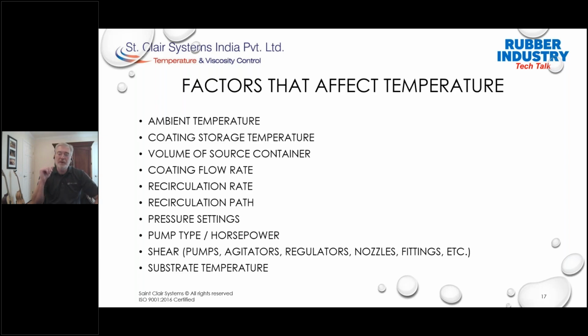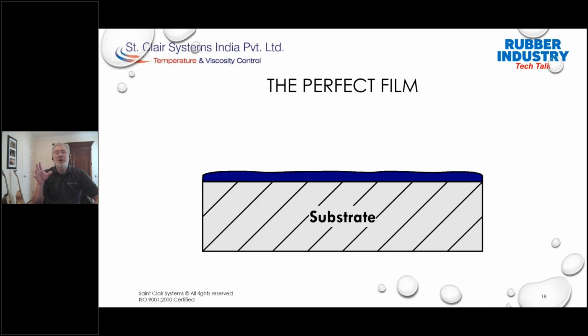So how do all of these temperature influences affect the film formation? If we're going to discuss film, we need to start with the perfect film. If the viscosity can be controlled and the system set up such that atomization and deposition and film build are even across the part, the cure will also be even and the result significantly more predictable. This more consistent surface will also produce a better bond.